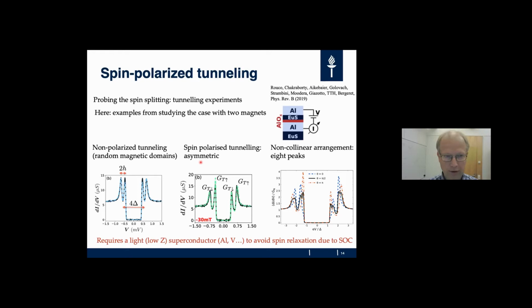But if you magnetize the system, you start to see the effects of spin polarized tunneling, where the tunneling probability through the system is different for spin up than spin down particles. In this case, these peaks sort of reveal the spin polarization of the conductance. Actually, the peak heights are proportional to it.